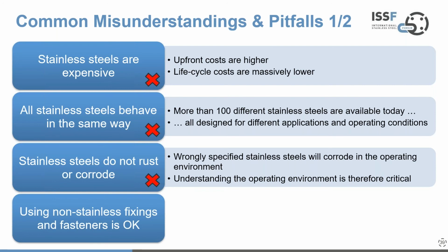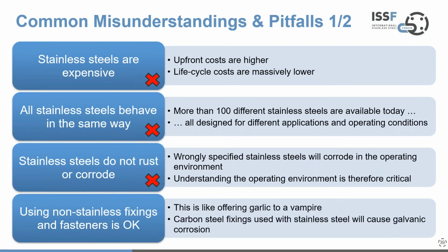And then lastly, using non-stainless fixings and fasteners is okay when you're working with stainless steels. I would say this is like offering garlic to a vampire. This is really a bad thing to do. An example I saw some years ago was a gentleman's urinal that had fallen off the wall 6 months after being installed using carbon steel fixings. And that's just an indication of how quickly things can deteriorate when you get galvanic corrosion occurring. So another red cross.